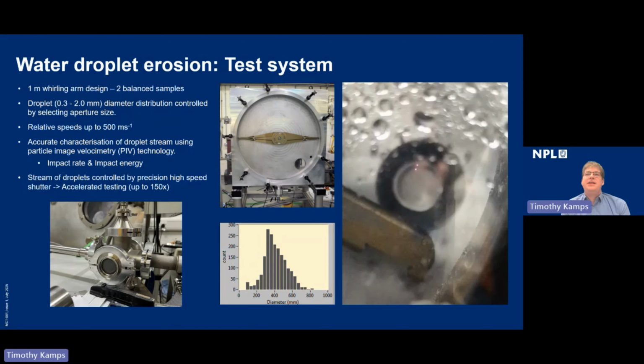As the arm rotates, it passes a jet of single droplets, which are traveling into the chamber. The chamber is evacuated to allow us to achieve high speeds of up to 500 meters a second. And we can achieve different droplet sizes by varying the needle from which the water droplets emerge. And we can achieve droplets from about 300 microns up to 2 millimeters in diameter.